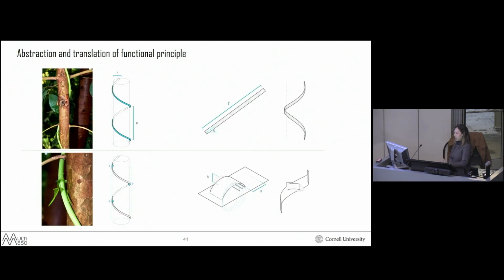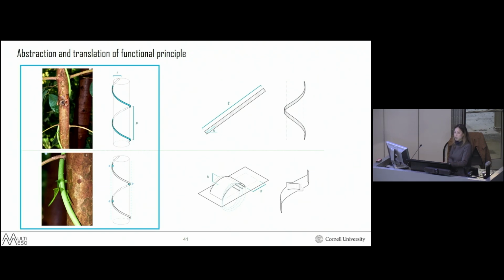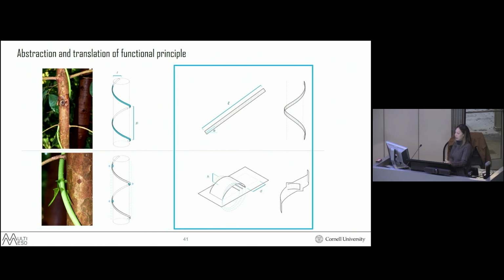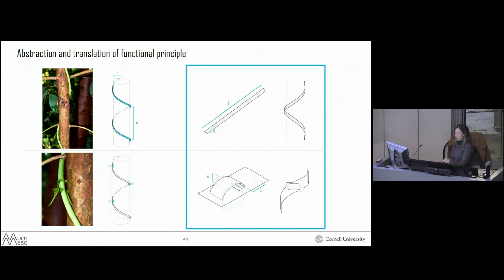So we then abstracted and transferred this tensioning mechanism to 4D printing. So the squeezing behavior is set up in two phases. The first, the stem helix loosely winds about its existing structure and then pushes outwards with the stipules in order to stiffen. Then we abstracted the functional principles and interpreted them, the first part as a twisting bilayer strip called the helix mechanism, and the second part as a bilayer flap called the pocket mechanism, which creates a pocket of space between itself and the helix on top of which it sits.